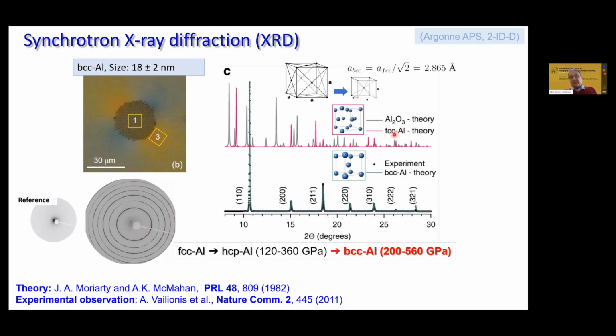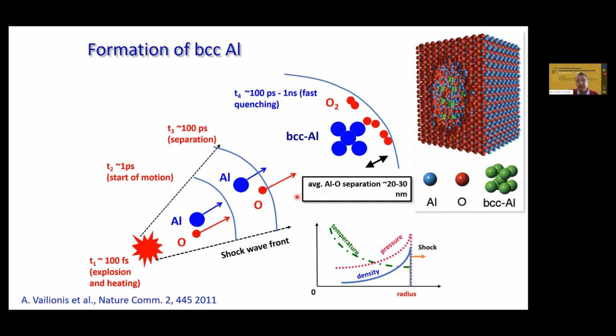Aluminum around us is always FCC, and in this experiment we see that this is a different phase. Here is a cartoon version of the explanation of how it happens. We start with an explosion, which is strongly localized, where aluminum and oxygen atoms and ions are ionized several times. They depart in this very fast dynamic explosion driven by pressure, and separation happens simply because of the difference of mass. Once it's quenched in that modified volume, you will see the BCC structure formed.